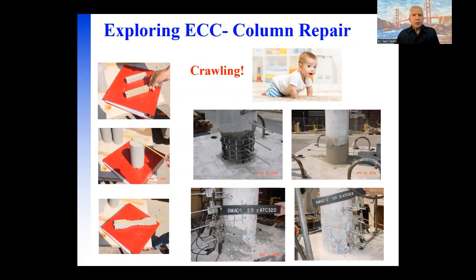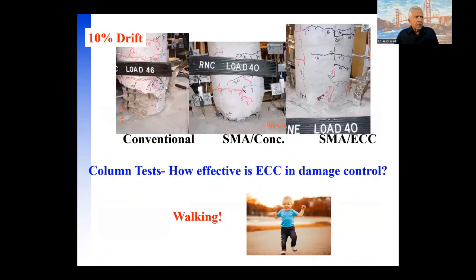So through that crawling, we learned that, yes, this material definitely has potential. So then we began to walk by saying, okay, let's just build some more columns and test these. And these are 3 columns that we studied, again, under cyclic loading. The one on the left side is conventional steel and concrete. The one in the middle has shape memory alloys and concrete. So here we did not use ECC in the middle one, but the one on the right side, we used the ECC and SMA. Again, you notice that the damage is substantially less than what you see in the conventional concrete. So we were convinced that, yes, this ECC is very effective in controlling the damage.